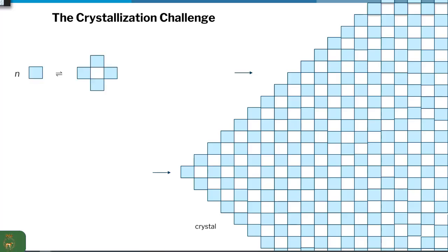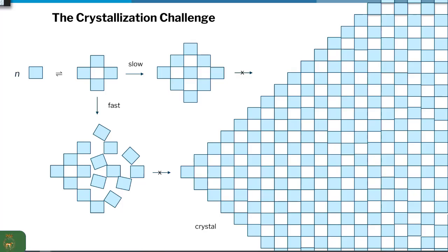but the crystallization problem has 2 components. It has a thermodynamic component where you need reversibility in linking building units together so that they can attach and detach and make sure that they come together in an ordered way. And you need to pay attention to the kinetics, because if it's too slow, the assembly is too slow, then you never get to the big crystal that you can characterize. If it's too fast, then they don't have time to be reversible, and therefore they make amorphous stuff. So that's what we were able to do.